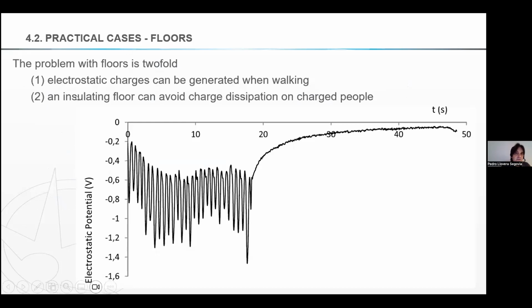There are two problems. Electrostatic charge can be generated when walking, but also an insulating floor can avoid charge dissipation on charged people. So they have the two problems. Electrostatic, this is a typical curve where people walking with non-antistatic shoes or on a non-antistatic floor have, at each step when you raise your legs, these voltage peaks, you are charging, and then when you stop, it takes some time to get discharged.